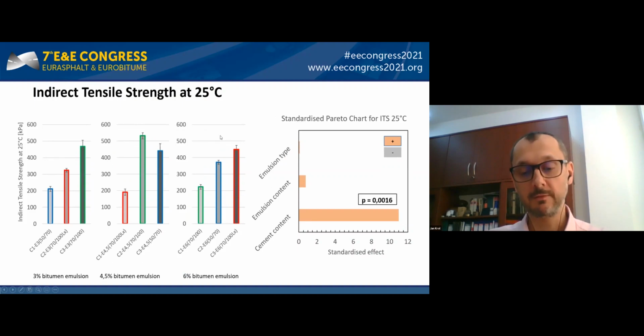Similar relationships are obtained for indirect tensile strength results. Similar values of ITS were observed for mixtures with the same amount of cement, regardless of the bitumen emulsion content. The largest standard deviation of ITS values was observed for mixtures containing 3% of cement. Statistical analysis shown on the right side has also proven that the cement content was the most important factor affecting indirect tensile strength of tested mixtures.